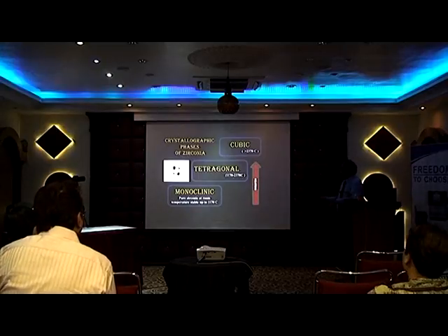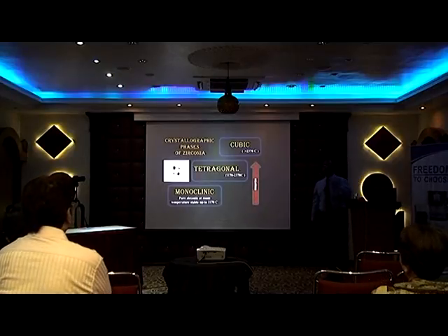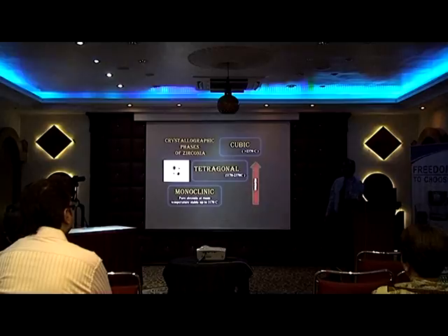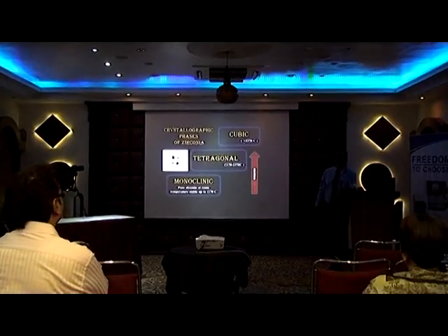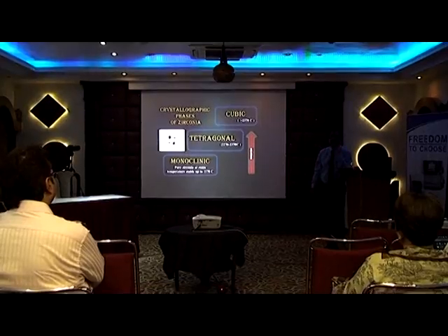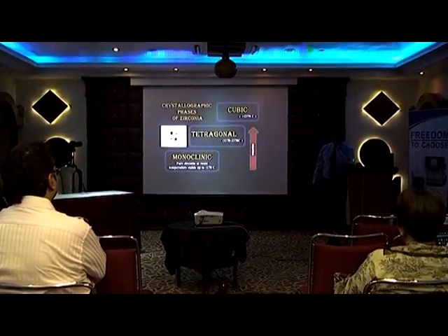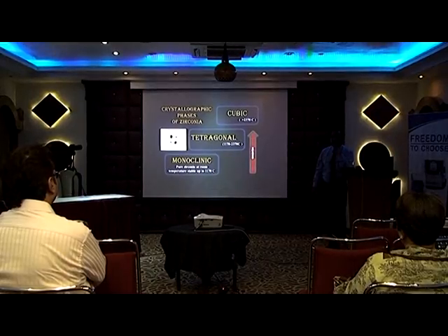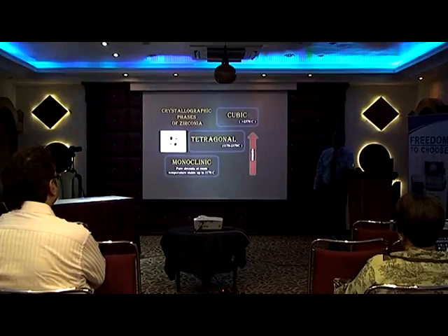So these are the phases. I'll just come back to it. This monoclinic phase is the weakest phase. The minute in your crown and bridge, you take an air rotor and you start grinding the tooth, I'm telling you the clinical application, the tetragonal phase, the minute you apply stress, changes into monoclinic. And monoclinic phase is weak, and that is where the fracture can take place. Why does the stress occur? If you see sparking coming out, that means you reached zirconia. Do not grind more than that.